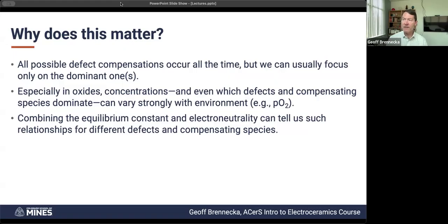So Shannon, great question about the bulk density. In that case, if you had oxygen vacancies versus titanium interstitials, in both cases the lattice parameter is actually going to grow a little bit because, strangely enough, vacancies are larger than having an ion there. It seems weird that having nothing takes up more space than having something. But if you think about it, that oxygen, if it's there, has titaniums around it, and the bonds holding them together pull those titaniums in towards that oxygen.